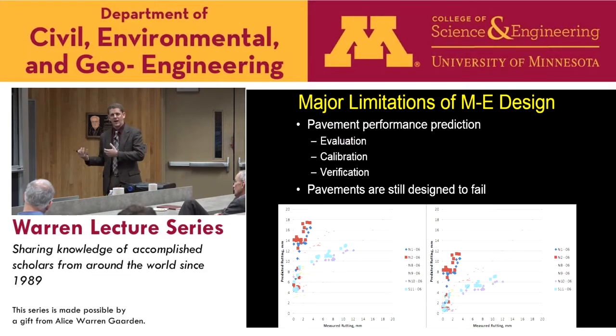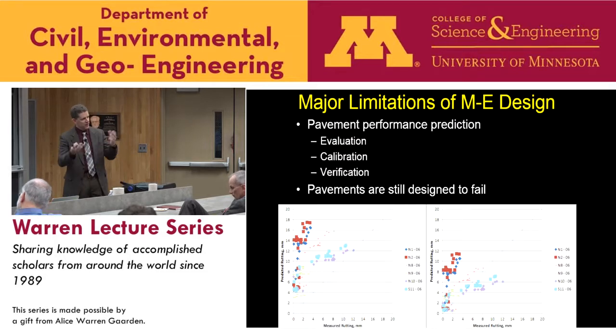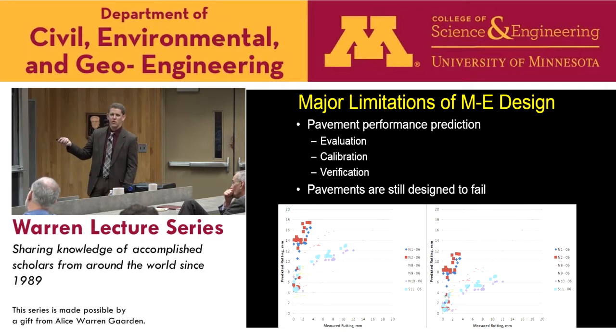At our test track, we're running trucks, we measure all of our inputs very carefully, and then we can look at measured versus predicted, and you can see that there's a lot of bias in that prediction. It's over-predicting rutting. If we were to just use the national calibration, we would over-design our pavements because it tells us that we're getting more rutting than we actually are. And so we go through the calibration process and adjust the calibration coefficients to try to recenter some of the data, as you can see here, okay?